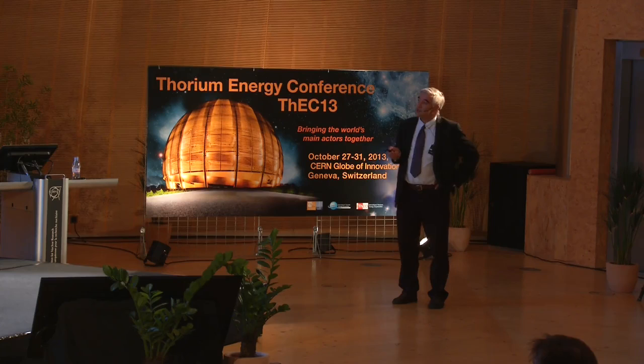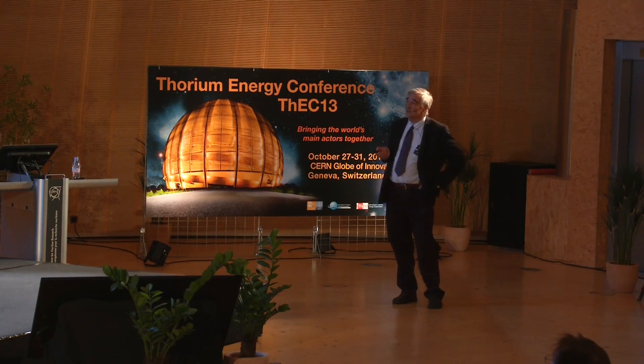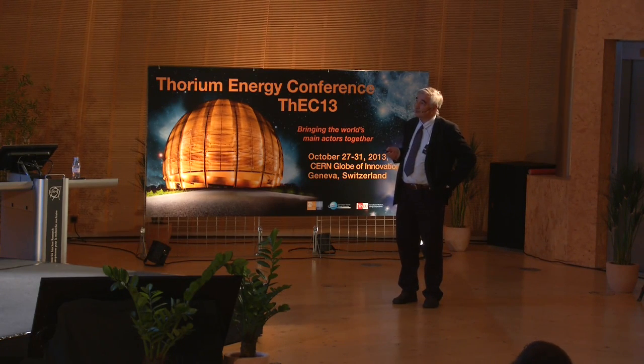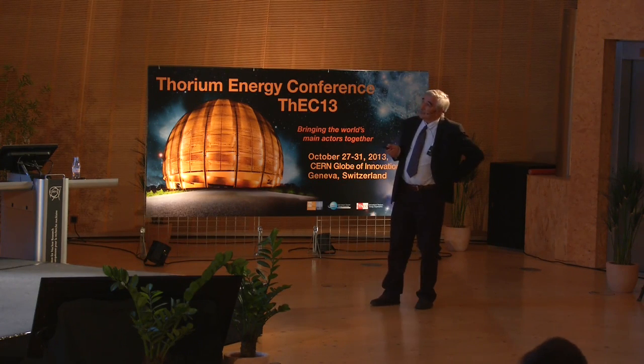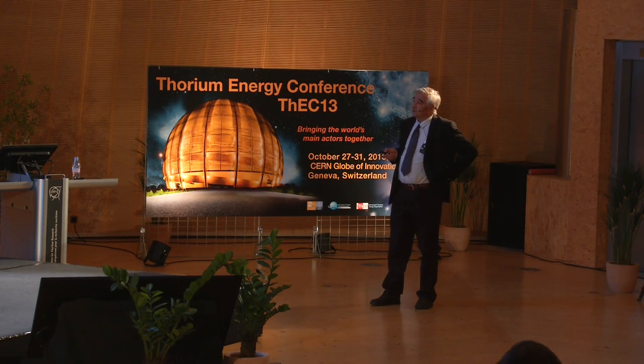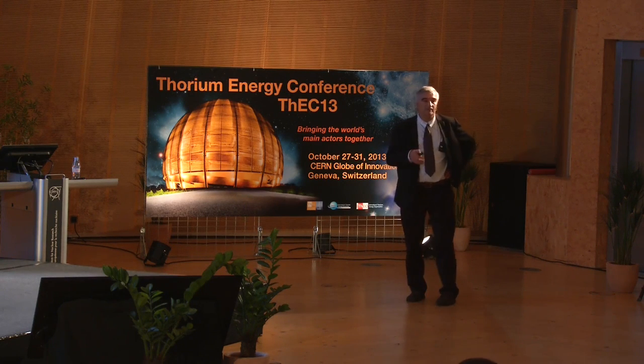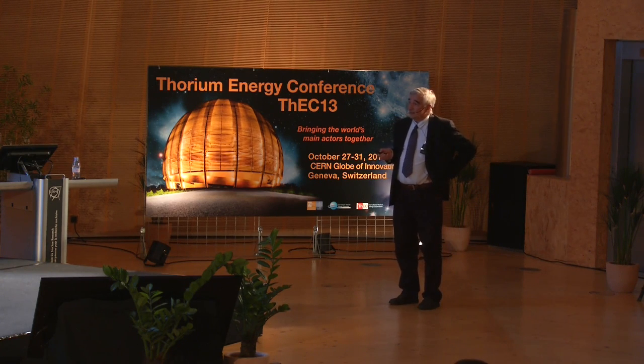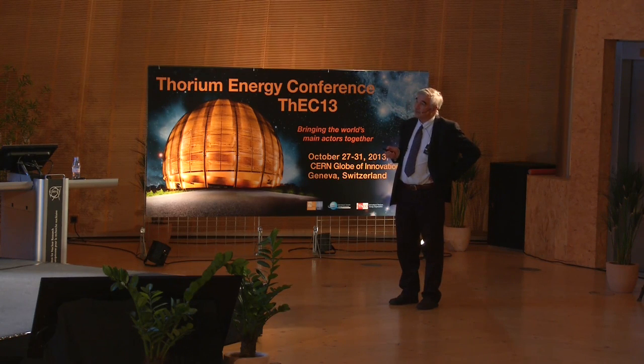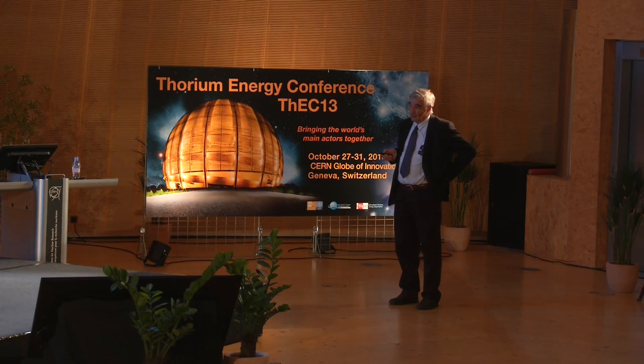So just to describe the target, it's about 4.5 meters height. There are 2 parts. Here, there is about 40 centimeters diameter, and here 20 centimeters diameter, more or less. It was operated between 230, 240 degrees for the cold temperature, up to 330, according to the design. We have a circulation of the lead bismuth going to the window here, just in front of the proton beam, and then the LBE is moving in this direction, going thanks to pumps to the exchangers cooled by oil. Then the LBE is sent back to the bottom. In order to avoid a static point here and a hot point, we have a bypass line with a second electromagnetic pump, which drives the LBE and perturbates the flow here in order to avoid any hot point.